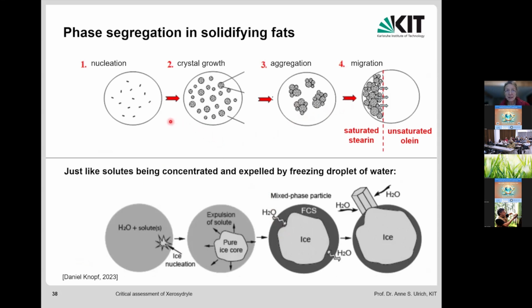And this has something to do with this melting and solidifying process that was used by the Pollack group to prepare the EZ layer. I think they did it to make samples really reproducible. But in fact, what must have happened is that a lipid mixture in the molten sample starts to cool down, and when it nucleates, the saturated lipids will nucleate out first because they have the highest melting point. So when the sample solidifies further, there's so-called crystal growth of these saturated lipids. They aggregate with each other, and in the end, on a little droplet or on a surface towards water, they push out the unsaturated oleic acid and polyunsaturated fatty acids because they have a lower melting point and don't like to sit side by side in a quasi-crystal lattice.